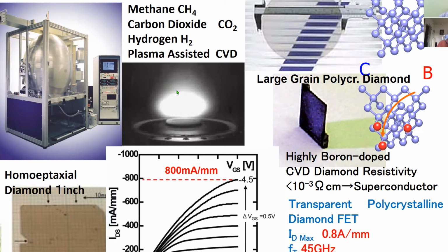For the plasma-assisted CVD, which is normally used in the semiconductor industry, this plasma is relatively high pressure, about 1/10 of atmospheric pressure. So the plasma is very dense and very hot, and the diamond could be made from that.